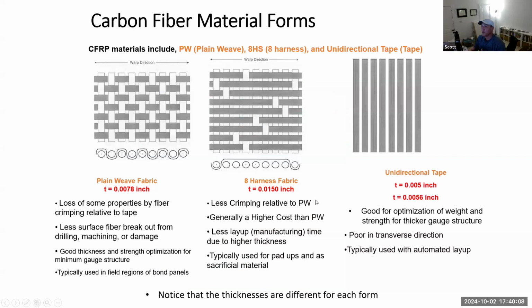So what are the carbon fiber material forms? You have plain weave, 8 harness, and unidirectional tape. Plain weave is basically fibers that go above and below, up and down, with fibers going in the opposite direction. So there's fibers going in the warp direction, and then there's fibers going in the fill direction. 8 harness is where you have a fiber going underneath and then over like 7 and then underneath. Unidirectional is self-explanatory. It's just fibers flowing in one direction. Notice the thickness differences between the three. 8 harness is the thickest, plain weave is second thickest, and then unidirectional is typically the least thick.